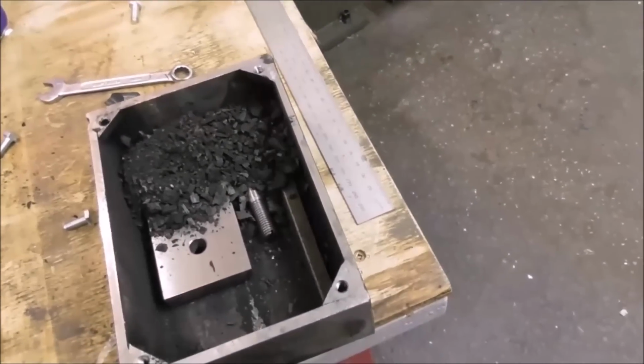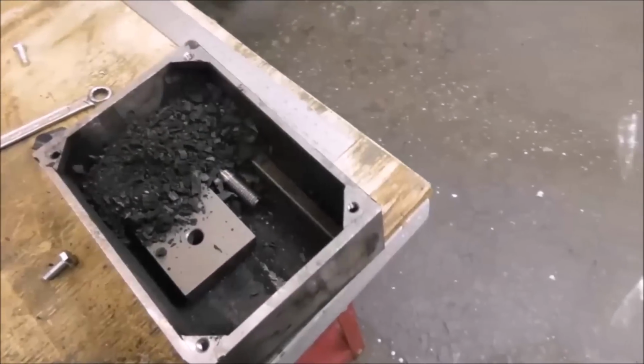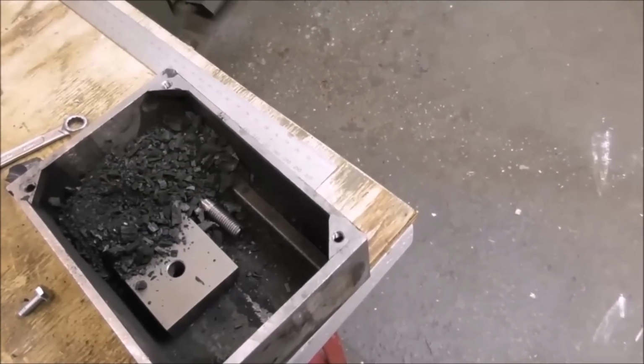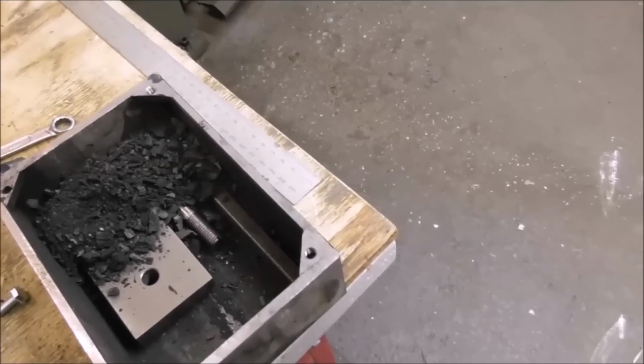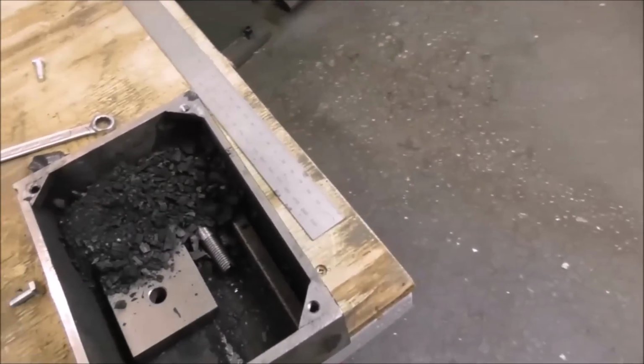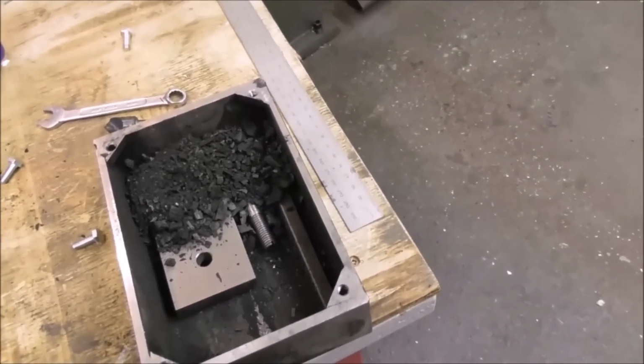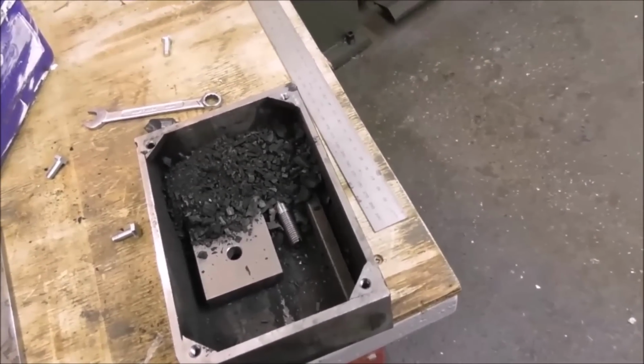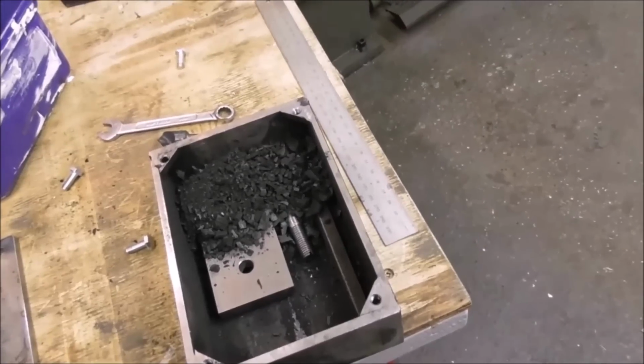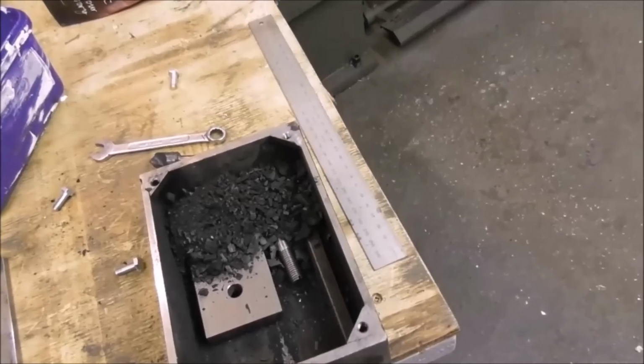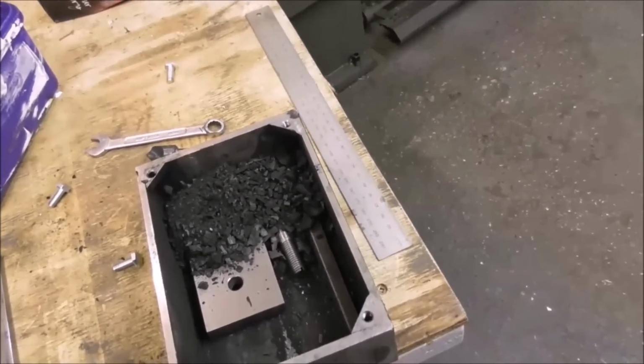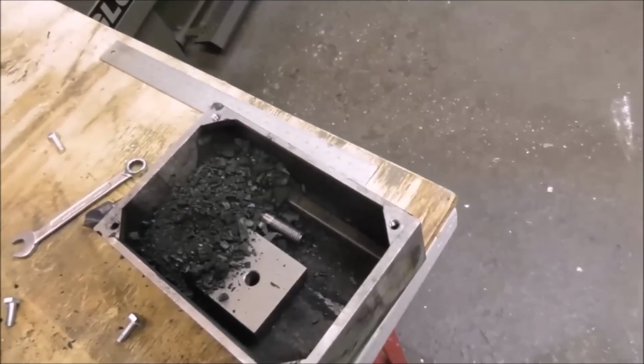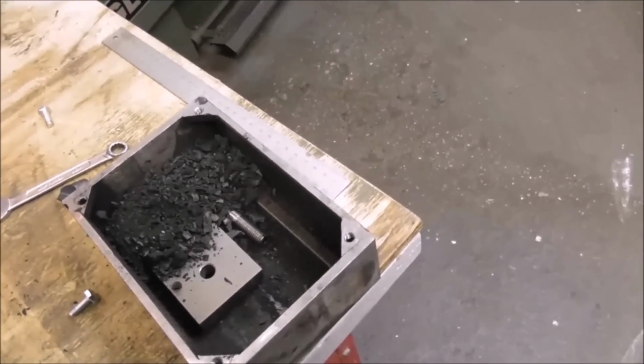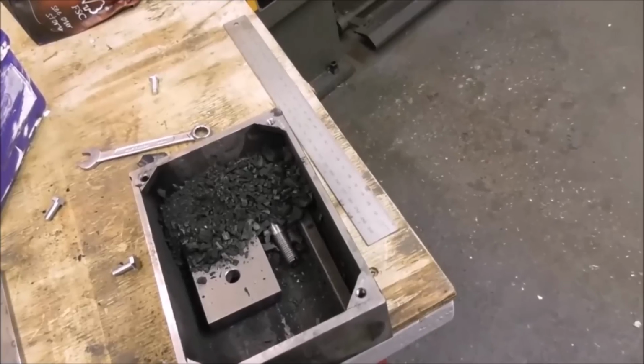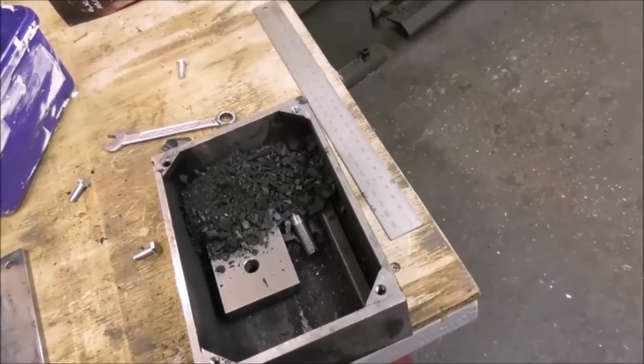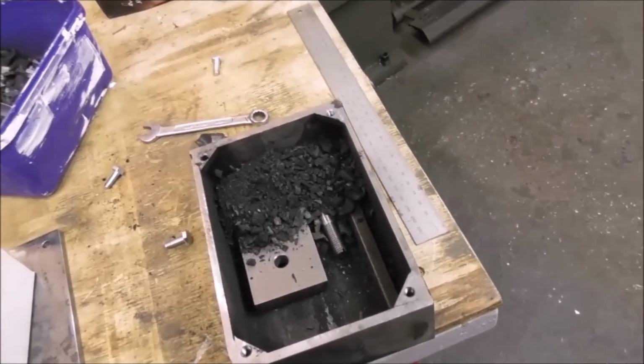I'll try partially covering it, and that way I'll learn a bit about how important the gas penetration is, whether it's covered or not. I'll put some bricks in there also to see how much I need, and heat it up to the temperature. I think it's about 920 odd degrees C. See how long it takes to penetrate in. Apparently it's about 0.1 of a millimeter, or a thou, per hour. I can do some tests to see what the depth penetration is. Perhaps I'll do it for about 4 hours initially, maybe 5 hours, and see if that gives me 0.5 mil of case depth. It'll be interesting to see how I go.